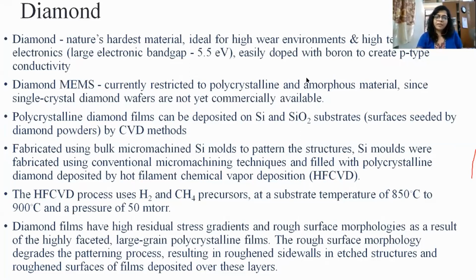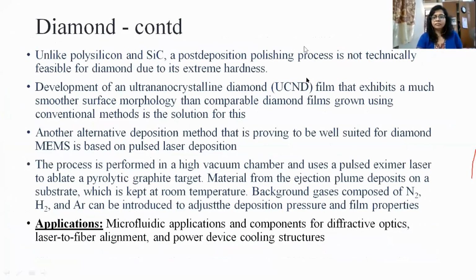of 50 millitorr. Diamond films have a high residual stress gradient and rough surface morphology, as a result of the highly faceted, large-grain polycrystalline film. The rough surface morphology degrades the patterning process, resulting in roughened sidewalls in etched structures and roughened surfaces of the film deposited over these layers.